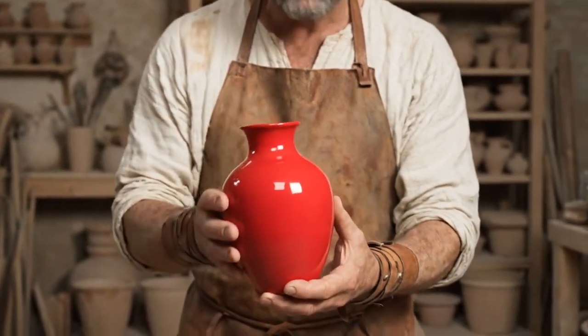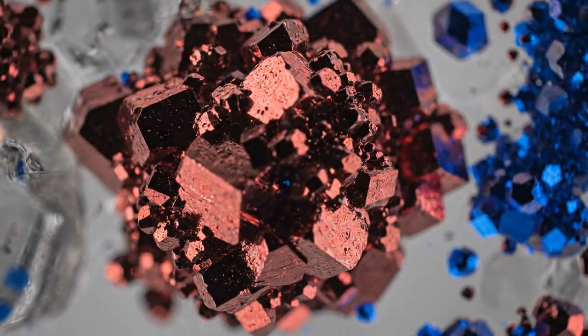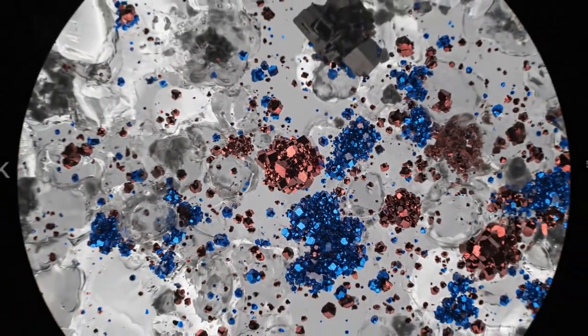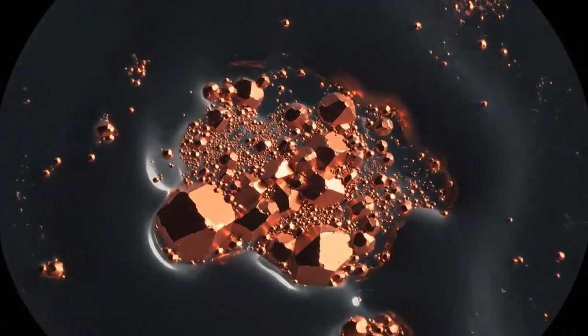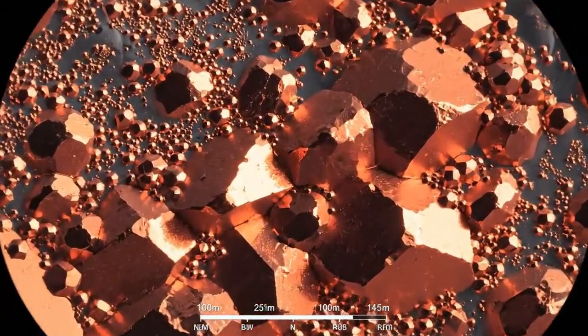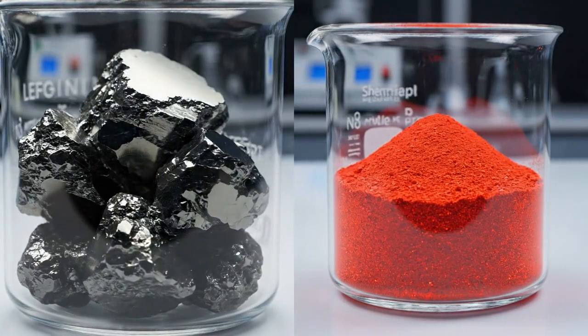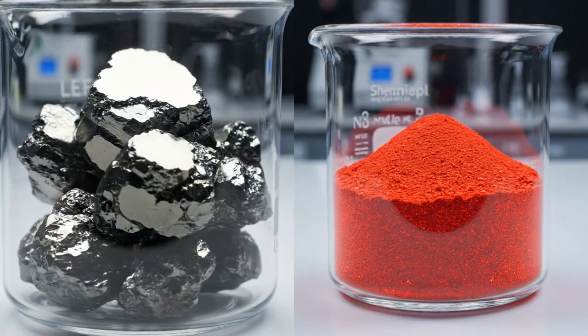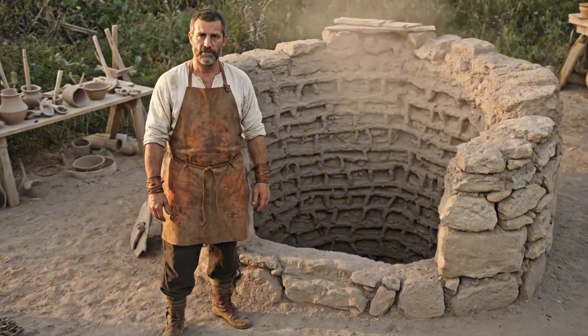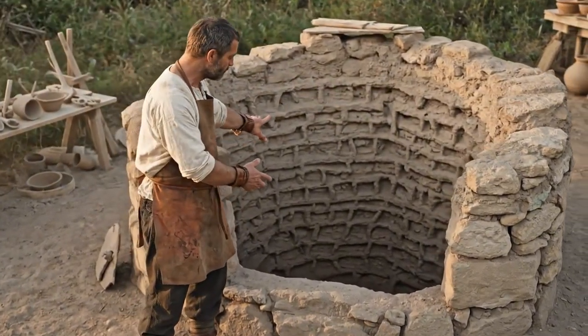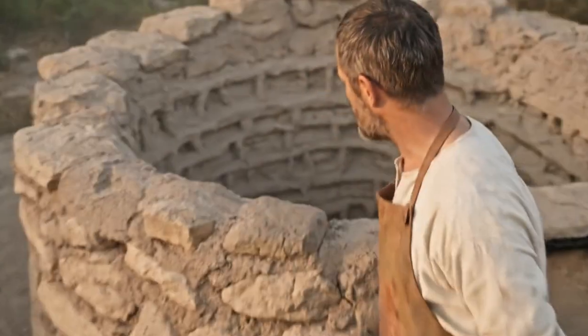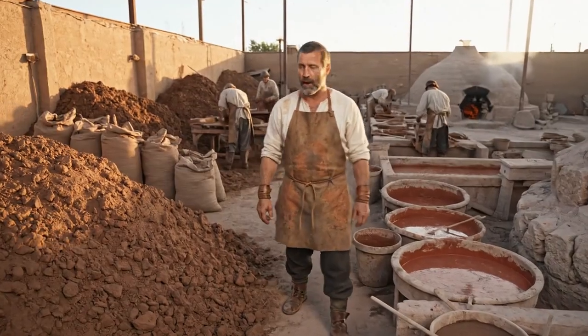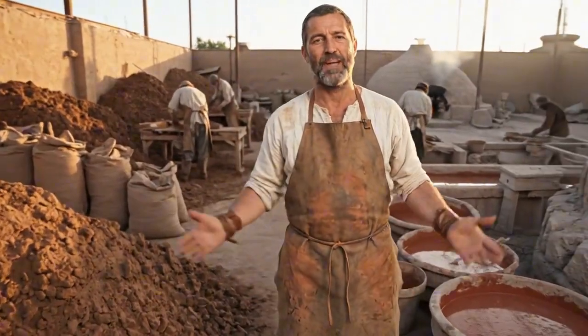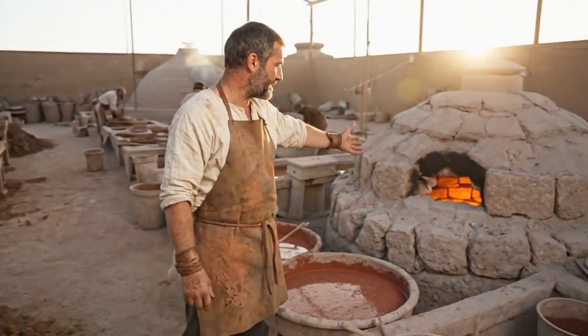Recent scientific analysis has revealed that the color of Terra Sigillata is not merely a function of iron oxidation state, but depends on the crystal size of submicroscopic hematite and corundum particles, suspended within a glassy matrix of silicon and aluminium oxides. Large hematite crystals appear black. As the crystal size decreases to submicron scales, the color shifts to brilliant red. The potters of Graufesenque, without microscopes or spectrometers, learned to control this nanocrystalline chemistry through the empirical mastery of raw material selection, slip preparation, and firing temperature.